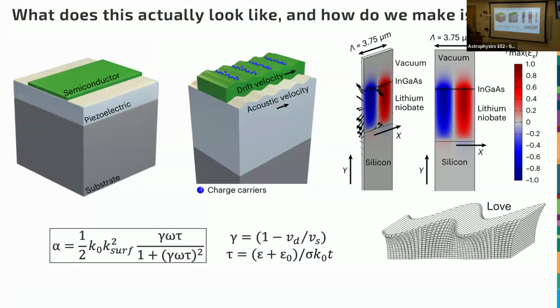I also need it to be, it turns out in the gigahertz frequency range, if you look at the available range of carrier concentrations you can get these semiconductors in, and the thickness available, the only way to make this time constant optimal for the acoustic wave frequencies you need to use is to make them very, very thin and very, very high resistivity. So I'll have a very low carrier concentration and a very, very thin semiconductor material. And that's the only way it'll work.